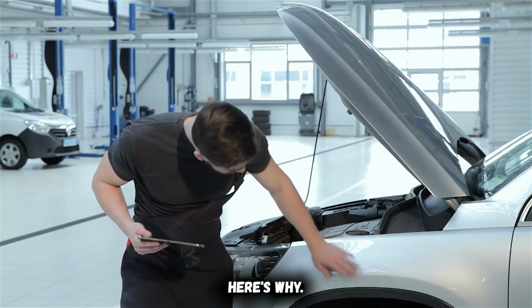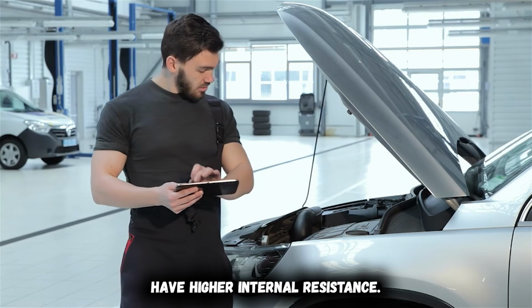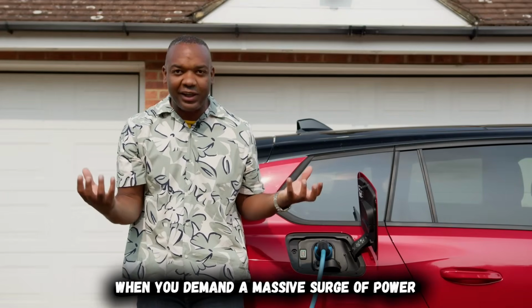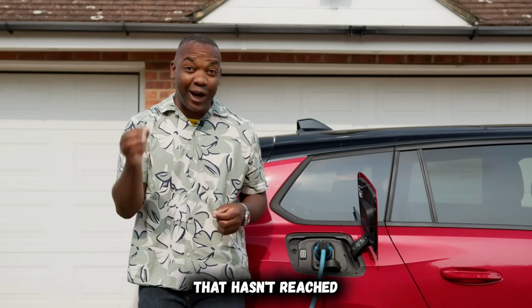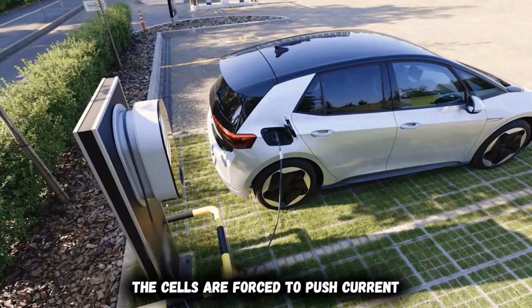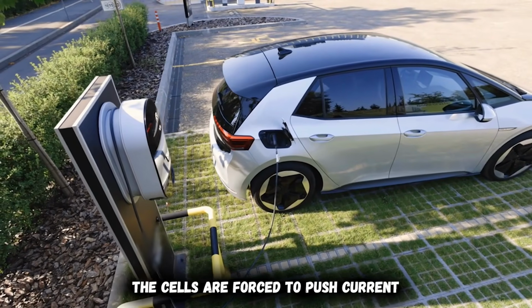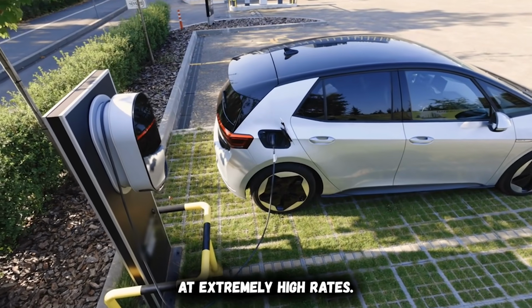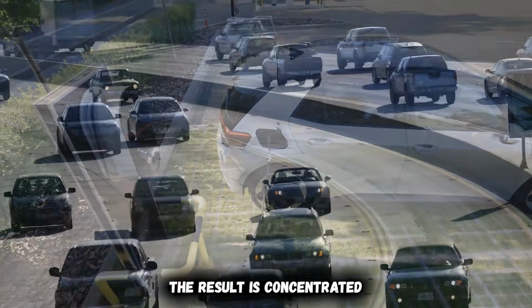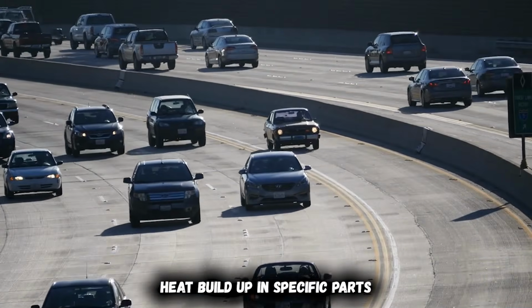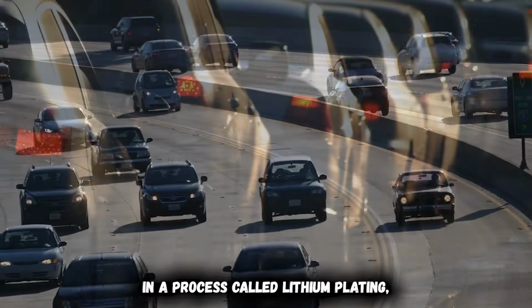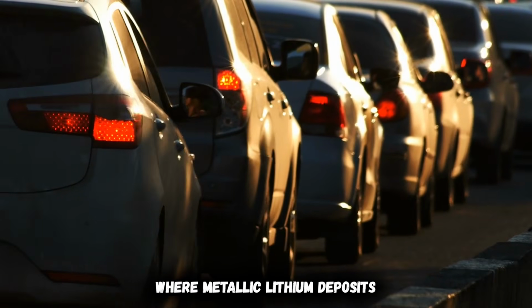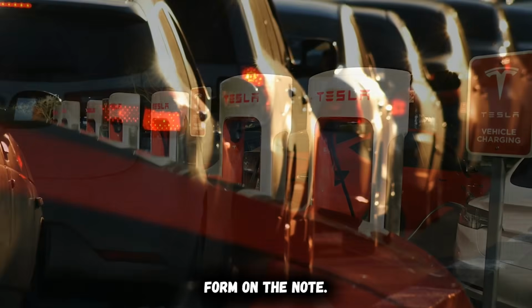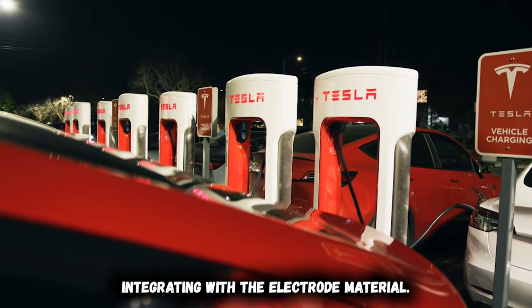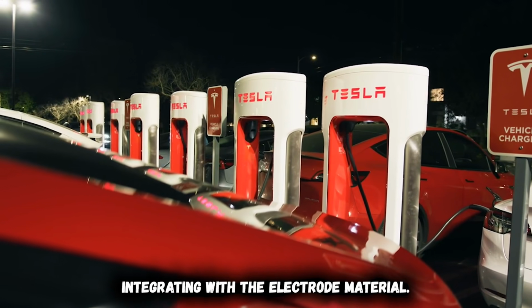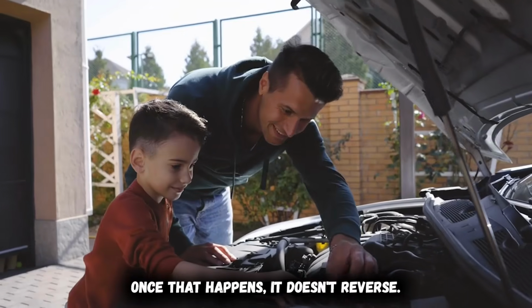Here's why. Cold lithium-ion cells have higher internal resistance. When you demand a massive surge of power from a battery that hasn't reached operating temperature, the cells are forced to push current through that resistance at extremely high rates. The result is concentrated heat buildup in specific parts of the pack, and a process called lithium plating, where metallic lithium deposits form on the anode instead of properly intercalating with the electrode material. Once that happens, it doesn't reverse.